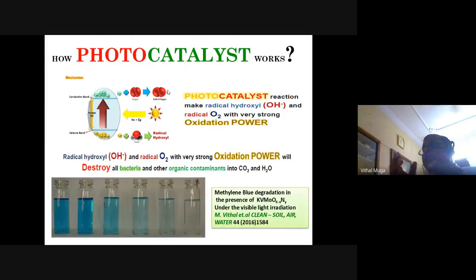For example, I will give a very simple example. In domestic electricity, we use pipes to cover the electric wires. But if you notice, after 10 years, if you just tap the PVC pipe, it will break into pieces. The reason is that the air contains many radicals. These radicals attack the PVC pipe, and PVC, polyvinyl chloride, is a polymer. Once the radical attacks, the polymer chain will be broken. Once the chain is broken, its strength will be lost, and therefore it easily breaks into pieces.